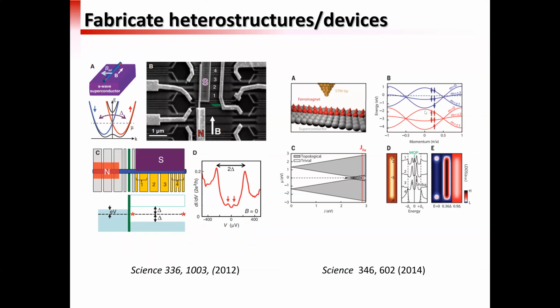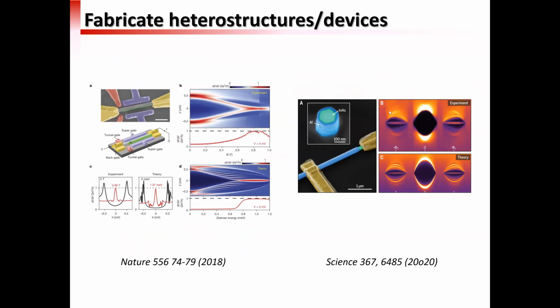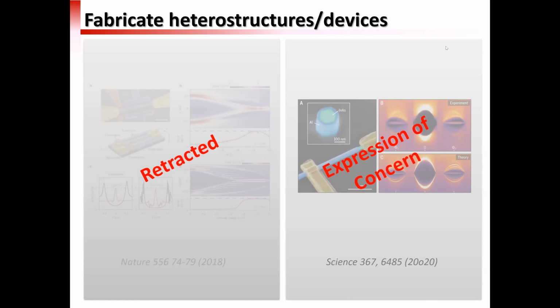And then there's also a 1D system, where people try to make nanowires and couple them with superconductors. This route also recently encountered some difficulty. It shows that although it's promising, there are a lot of details in the device fabrication and the measurement that people need to be very careful about. This is not necessarily a bad thing, this retraction and expression of concern. It just means this is a difficult subject, and we should motivate and get more people in the field and also get more resources for doing this.